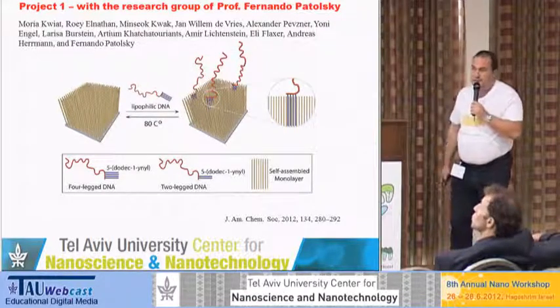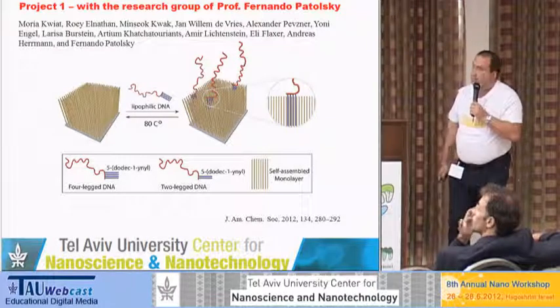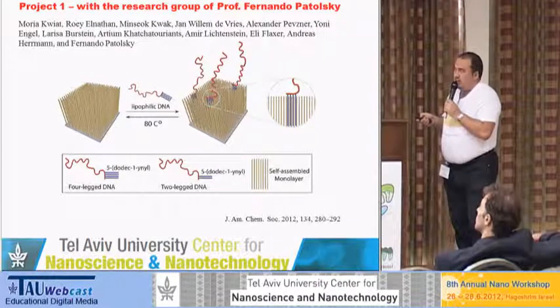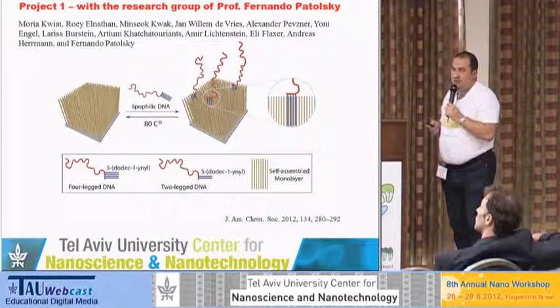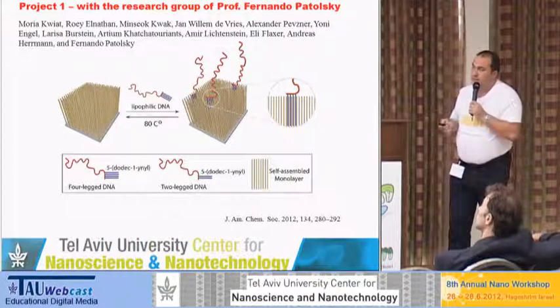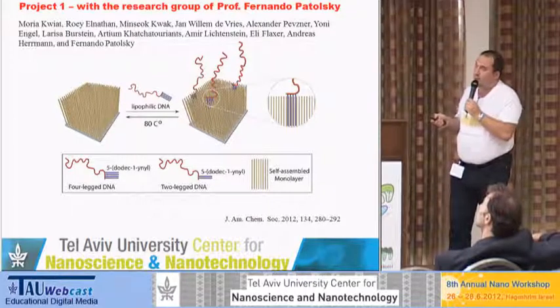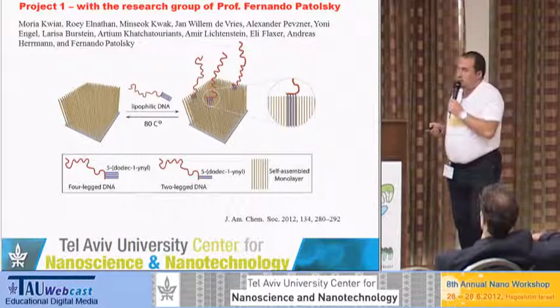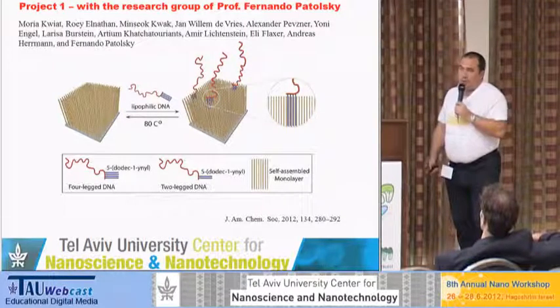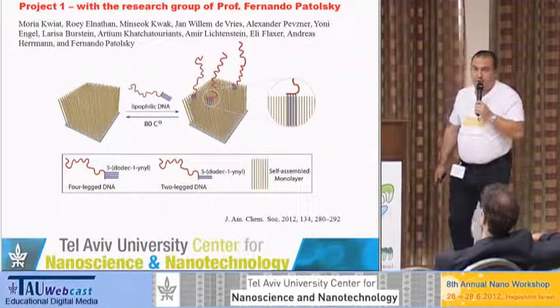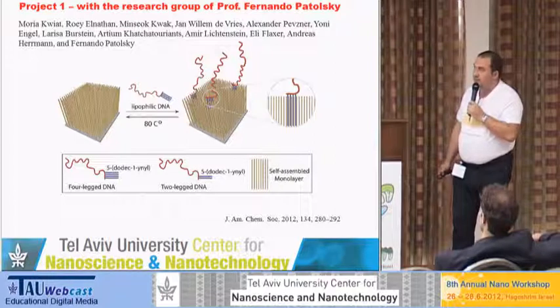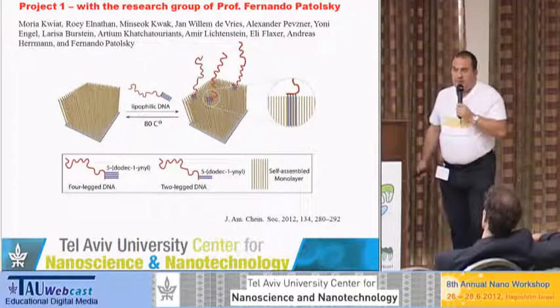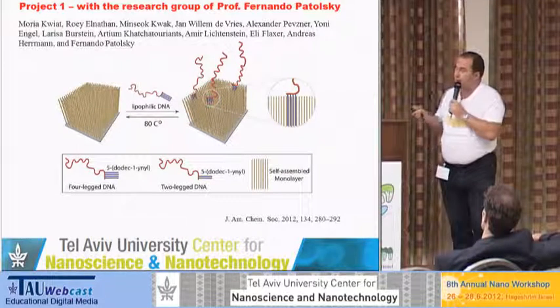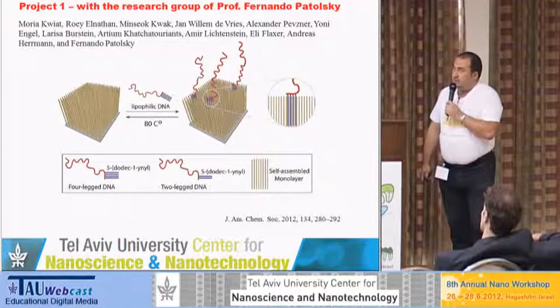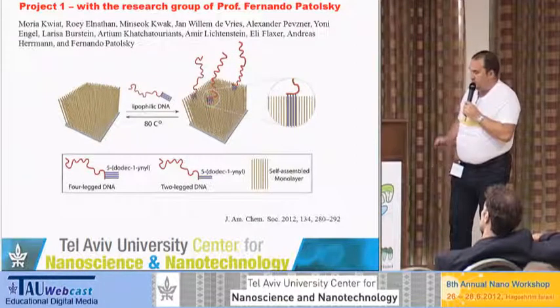And this process appears to be controllable by the incubation time, the density of the concentration of the amphiphilic DNAs, and also reversible, which is very important. By just heating it to 80 degrees centigrade, one can release these DNAs and stay with the original self-assembled monolayer without compromising its original properties. So one of the important tasks in such research is to characterize such surfaces, and they are characterized by different techniques, including fluorescent confocal microscopy, if you link some fluorescent dye to them, or they are characterized by X-ray techniques.